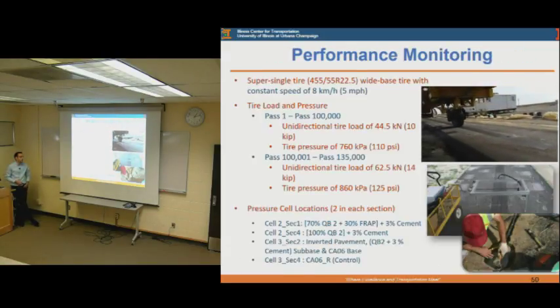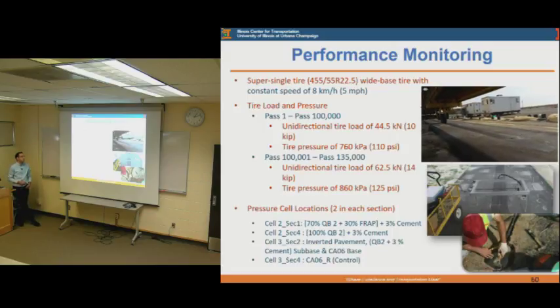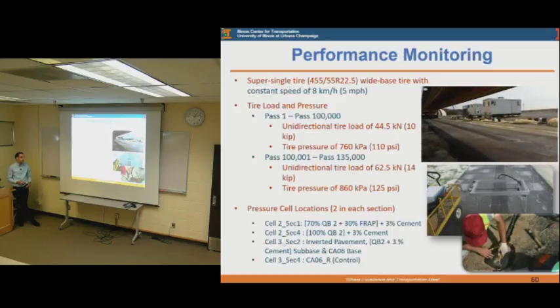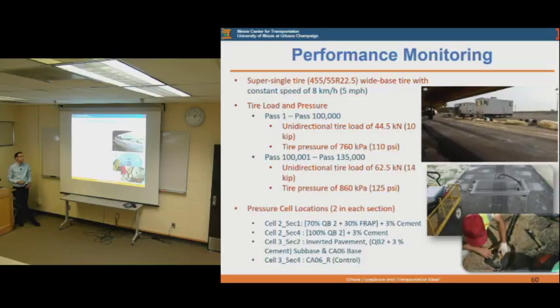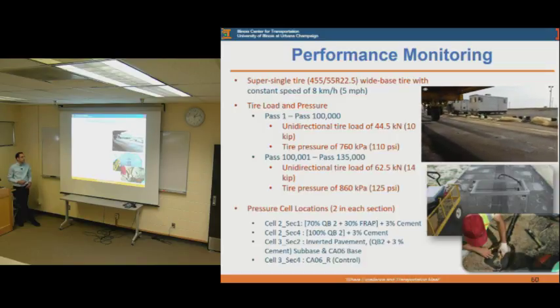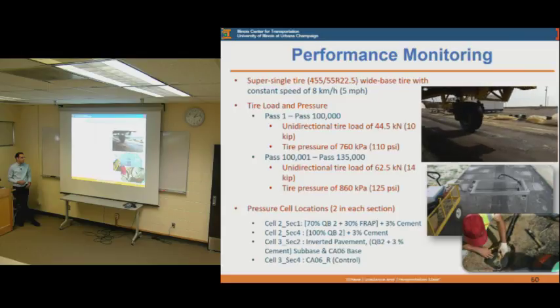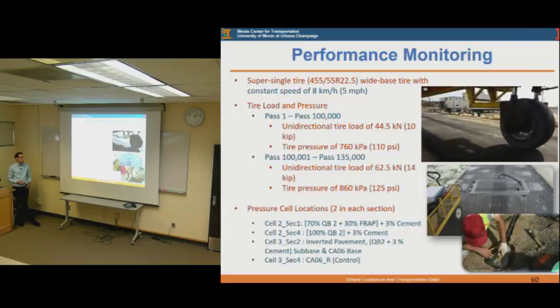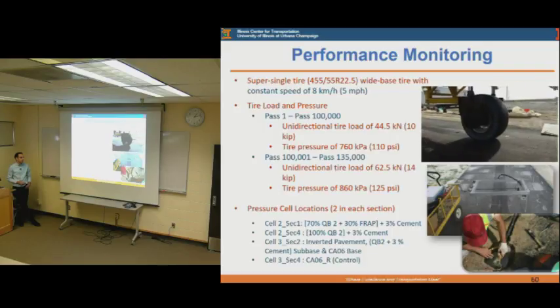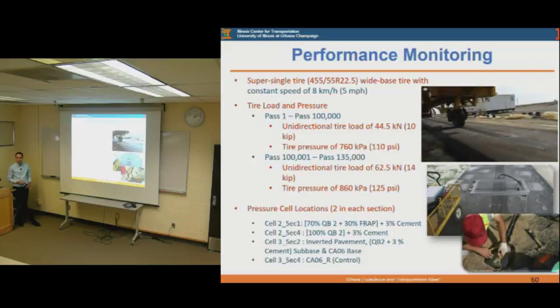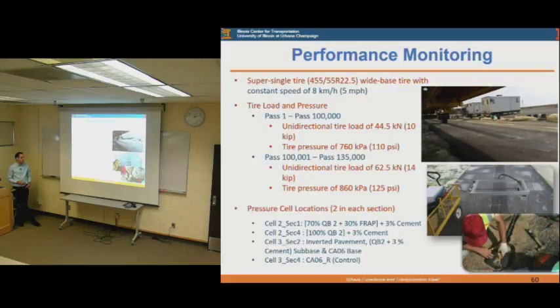Again, also performance monitoring of the test sections, in a similar manner. This time we went to a larger number of passes, because we had better performance of these test sections, and some of them had a very good performance. So for the first 100,000 passes, we were using the same loads and the same tire configuration and pressures as we were using for cell 1. But especially for cell 2, which we have completed now, we wanted to test it for a higher number of passes and increase the load and the tire pressure in order to see if we can accelerate the damage even more, because some sections had very good performance.